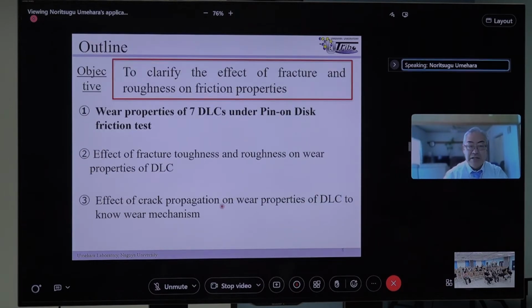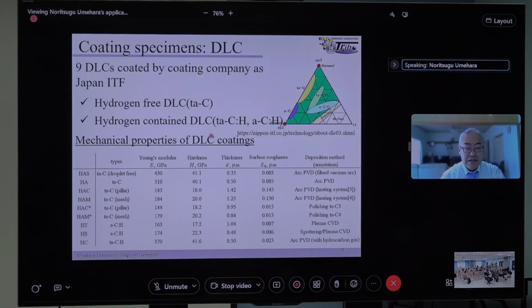Finally, we have analysis. The objective is to clarify the effect of fracture and roughness on friction property. Why roughness? Roughness can change the surface stress so much. So at first we have done 7 different DLCs for the pin-on-disk friction test. The 7 different ones are not only hydrogen-free DLC, but also hydrogenated DLC, and also dopant-free or doped ones. We have also changed the surface roughness. So we have used such different DLC materials.